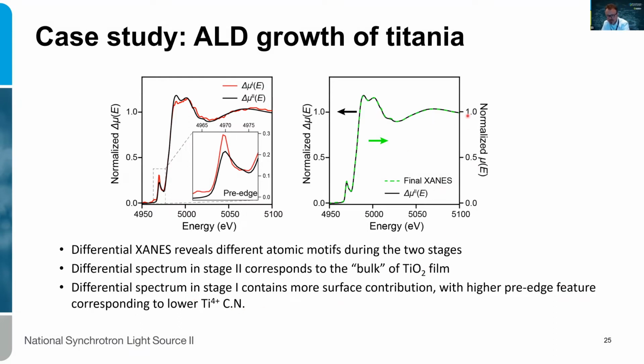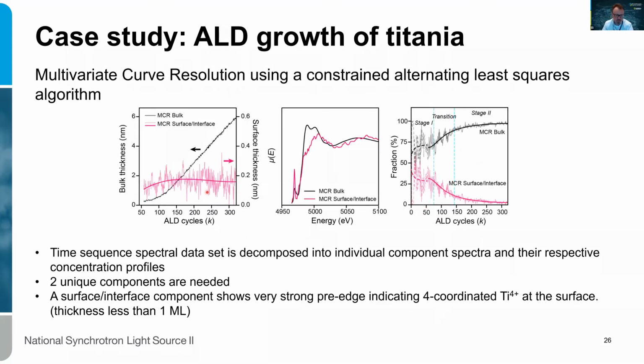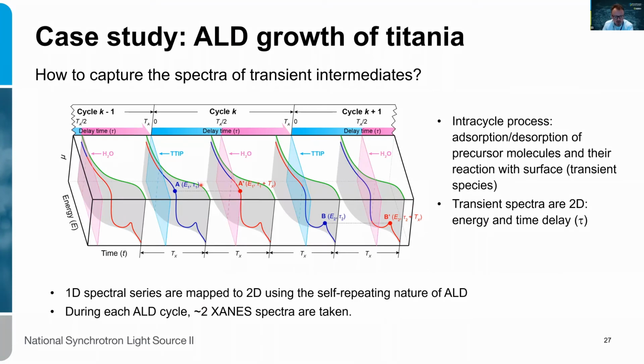So now, this is the comparison of the final XANES and this differential signal. Now we can apply the same MCR to the stack, and we are extracting two components out of this. There's the bulk signal, and then the transient signal that starts up and then almost doesn't go away with the progress of the process. And this is our signal from the surface or the interface, these under-coordinated titanium atoms that are at the very interface of the growth. And this is how they behave, this is the fraction. It's just another representation of this picture. So we need two unique components in this process, and the thickness of the thin one is really lower than one monolayer.